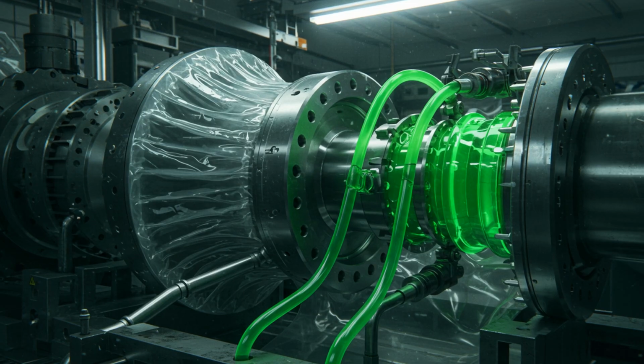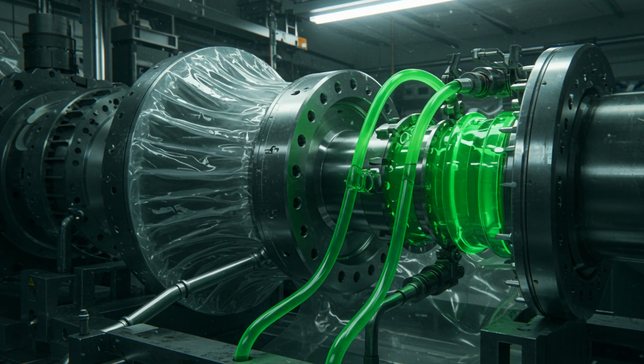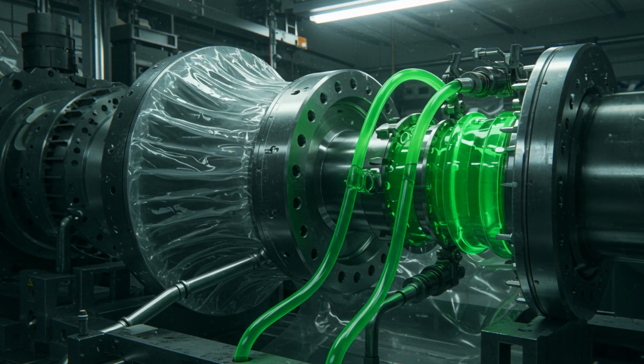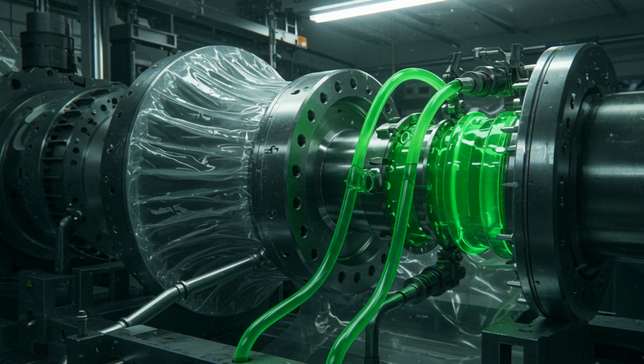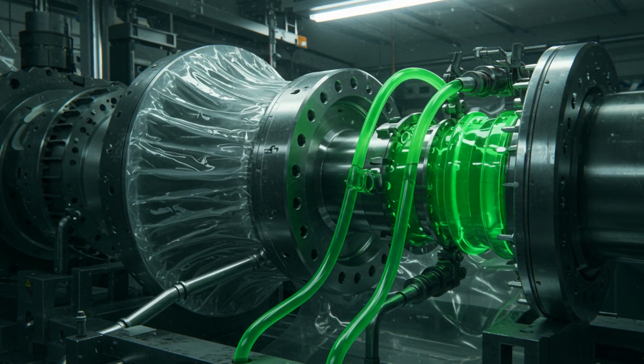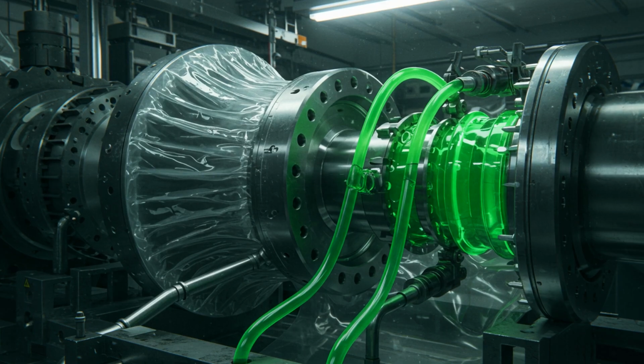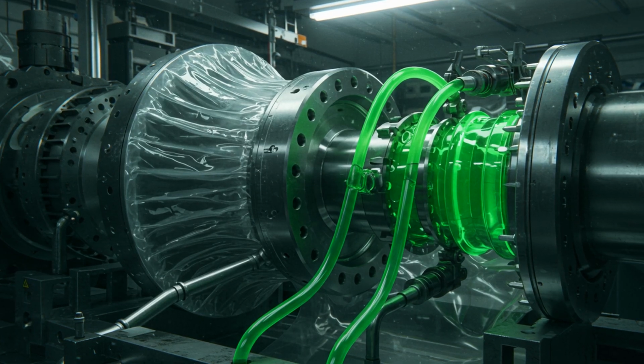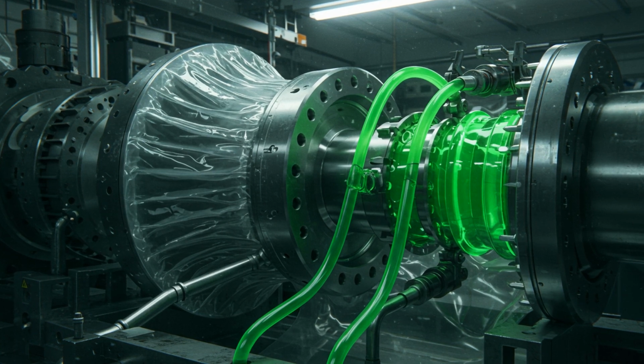This process, known as vacuum-assisted resin transfer molding, is remarkably efficient. It ensures there are zero air bubbles or voids inside the laminate. Air bubbles are the enemy of composites. They act as starting points for cracks. The resin flow is monitored by thermal cameras and flow sensors, ensuring the liquid reaches the tip and the root at exactly the right time. The chemical reaction is exothermic, meaning it generates its own heat as it begins to harden. The blade is literally coming to life through a controlled fire of chemical bonding.